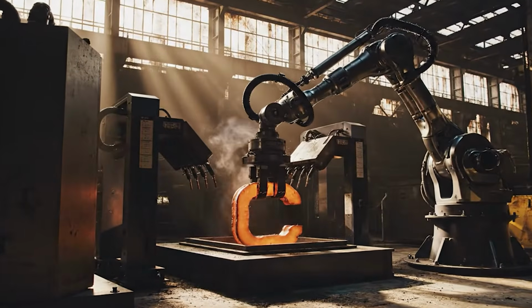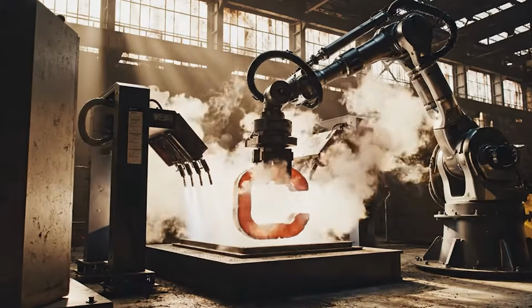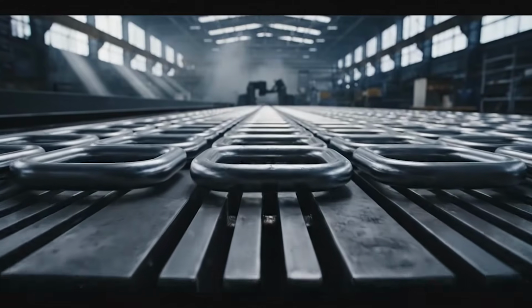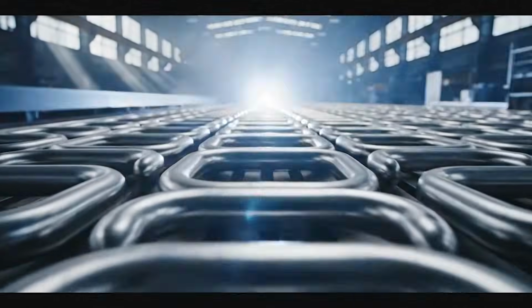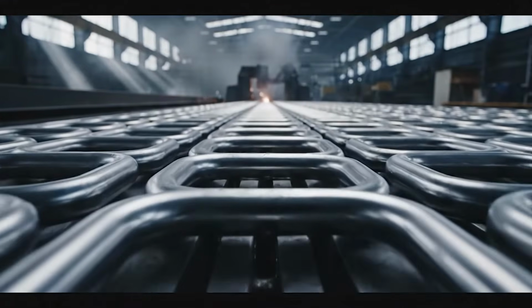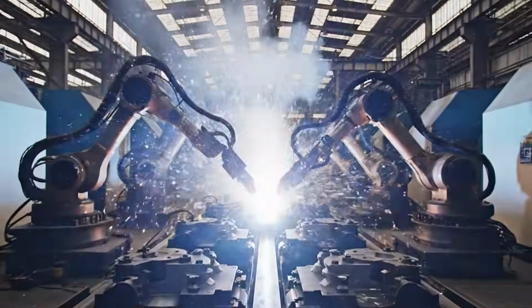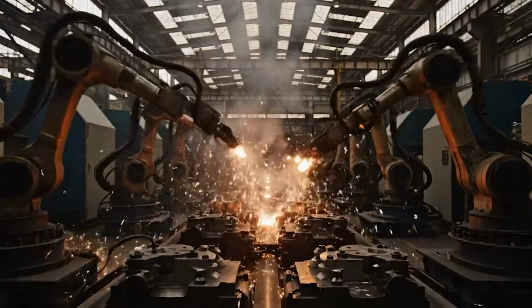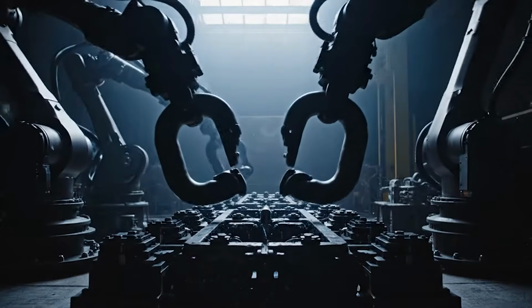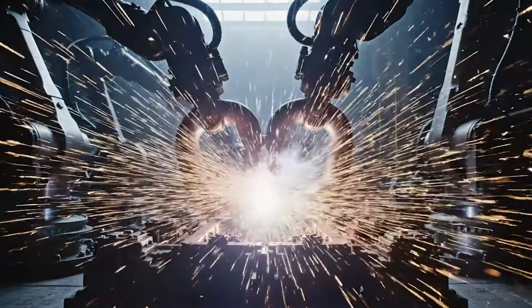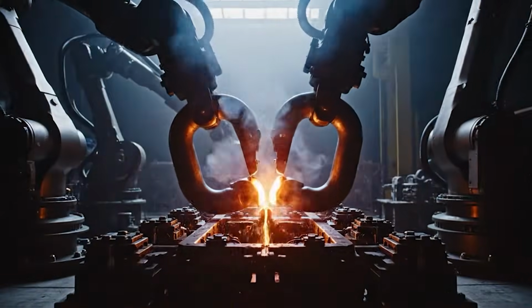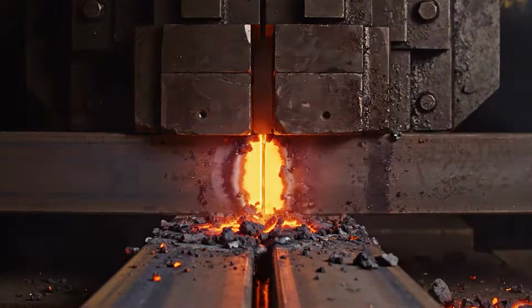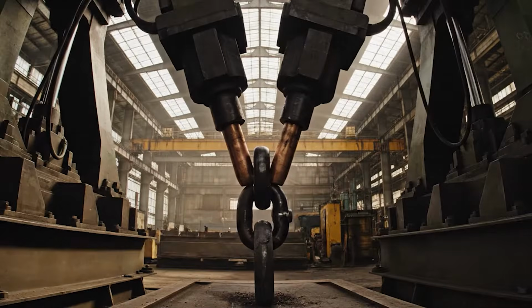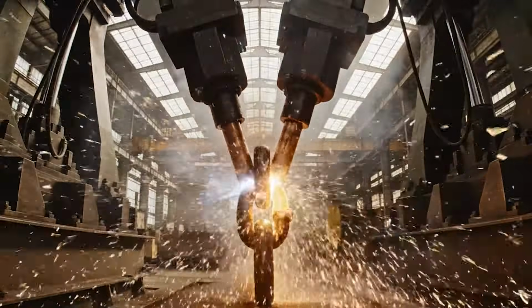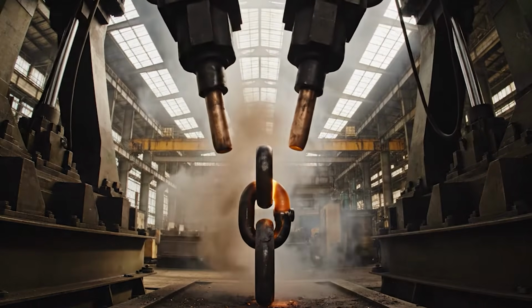The most critical moment in building a chain, the weld. The open ends of each C-shaped link are pressed together inside a flash butt welding machine. A massive electric current surges through the steel, and instantly, sparks erupt, white, bright, and violent. The metal edges heat to over 1,500 degrees Celsius. They soften, melt, and fuse into one continuous loop. When the welder releases pressure, the link is no longer open. It is sealed forever. Robotic grinders remove the excess weld bead, creating a smooth, seamless finish. If done correctly, the welded area becomes stronger than the rest of the link. If done poorly, it becomes a ticking time bomb. To guarantee safety, every weld is scanned, measured, and recorded.